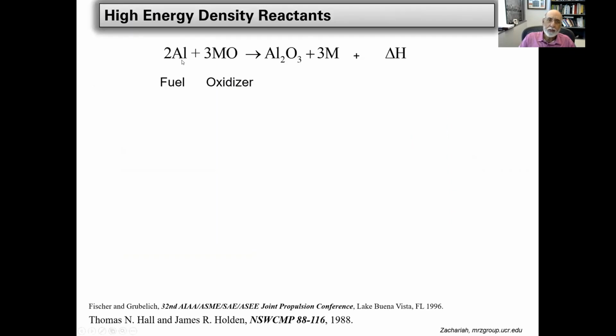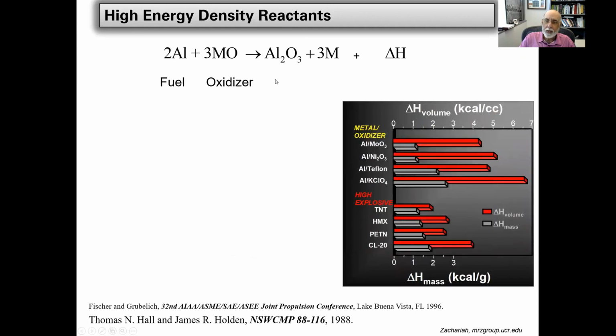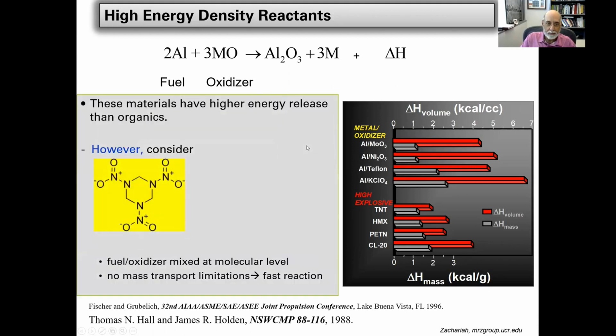So these reactions, as I said, are very high energy density. Just to do a comparison, here's thermodynamics of metal oxide. These are aluminum plus molybdenum oxide, or aluminum plus potassium perchlorate. And then I'm comparing that with what we consider high energy dense materials, explosives. And you'll see that the energy density of these metal oxide systems is usually about a factor of 2, depending on the metric, relative to the higher explosive. So in terms of energy density, these kinds of materials are the best you can do right now. However, the kinetics are slower.